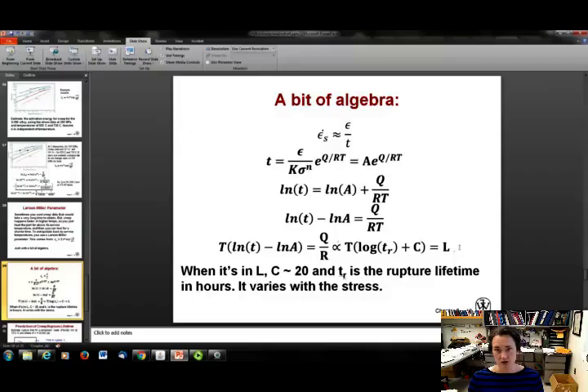So our Larson-Miller parameter L is the temperature times the log of the time to rupture plus some constant C. And your book tells you that this constant C varies a bit, but it's about 20. I'm sure if you went through and did the math, you could figure out why it's about 20. The rupture lifetime is usually cited in hours, and it varies with the stress.